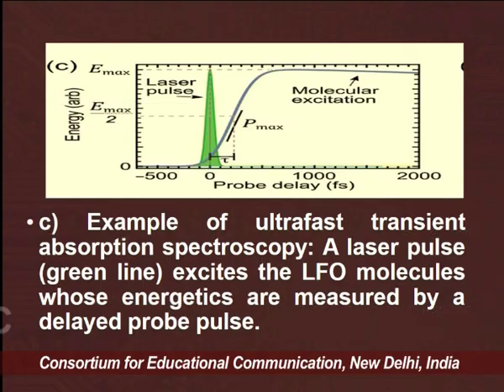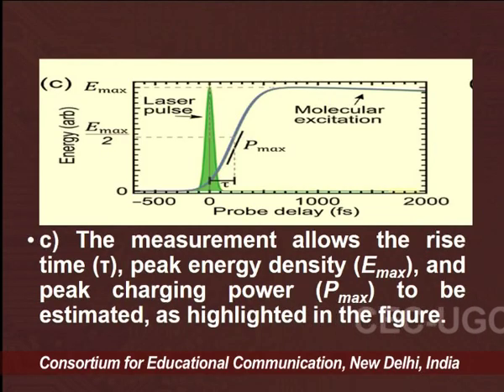You can see here the probe delay, and on the left-hand side we have the energy, how it is delaying. So, that is a molecular excitation, and that is a delay that will define a laser pulse exciting the LFO molecules. So, the measurement allows the rise time, defined by tau, the peak energy density, defined by E maximum, and the peak charging power, defined by P maximum, to be estimated by using this graph.